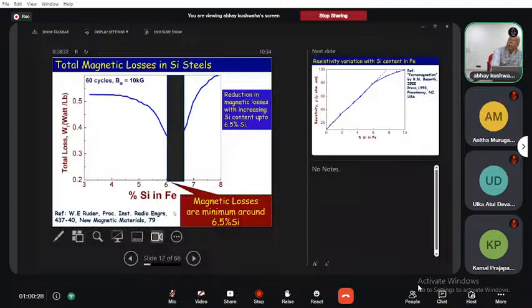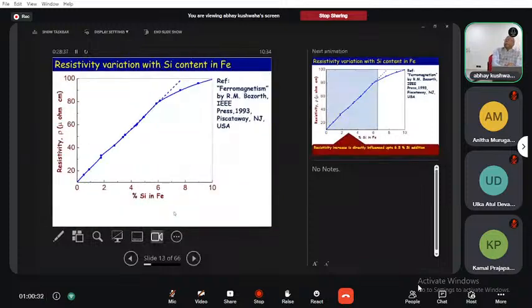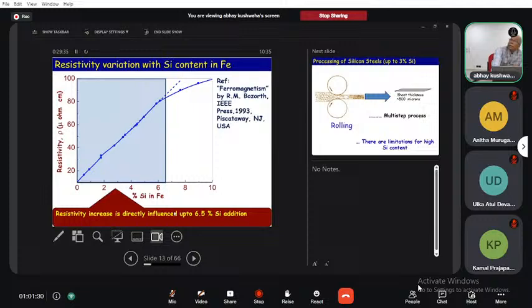And then if we go to the resistivity measurements, why is resistivity important? Because if the material has a high resistance, then the eddy current loss will be less. The loss here is I square R, so if the resistance is high, then I will also be less, because the loss varies with the square of the current magnitude. So if I is less, then the eddy current loss is also less. But again, you can see it increases linearly up to around 6 to 6.5, and after that it deviates from linearity.